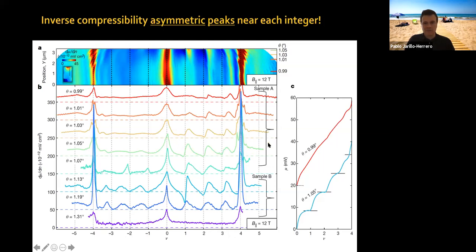This is again for sample A and for another device, sample B. This is the second device, which is of much higher quality, and you can see many more features. We're only showing a subset here. These are data at finite parallel magnetic field, because for device A the features were stabilized under a parallel magnetic field. But in sample B, I'll show you data in a moment, all of these features are there even at zero magnetic field. So you can see that the features in inverse compressibility vary a lot with very small twist angle variations, okay? And this is again a local measurement, so the twist angle is uniform in the local region where we're scanning.